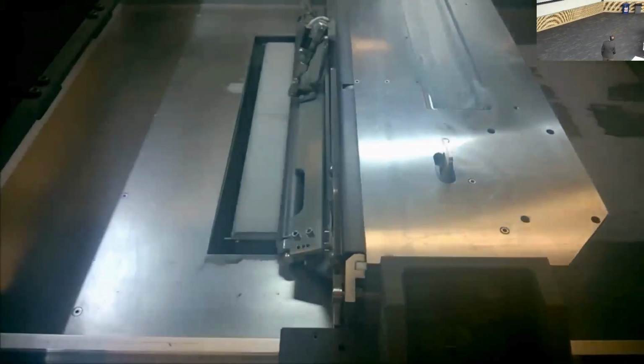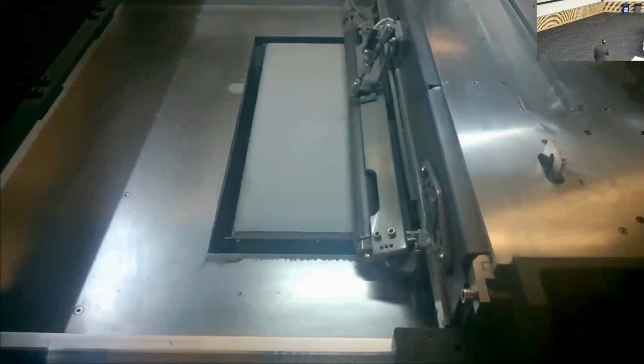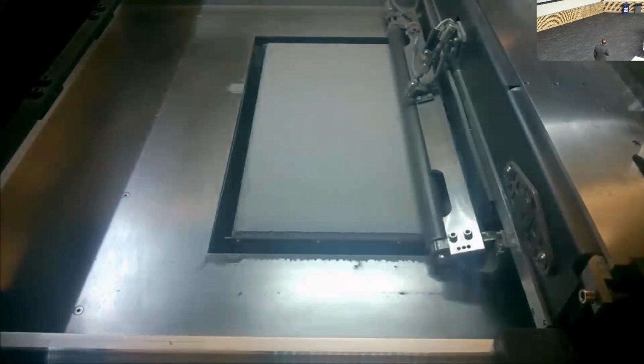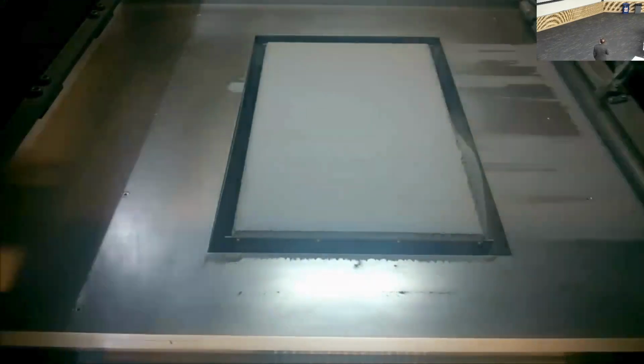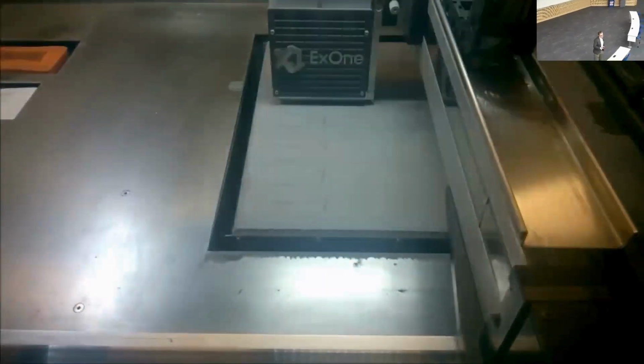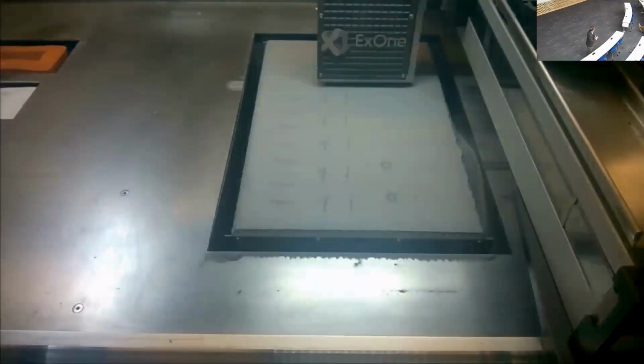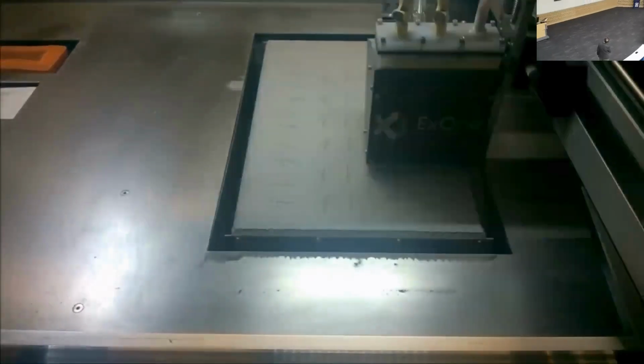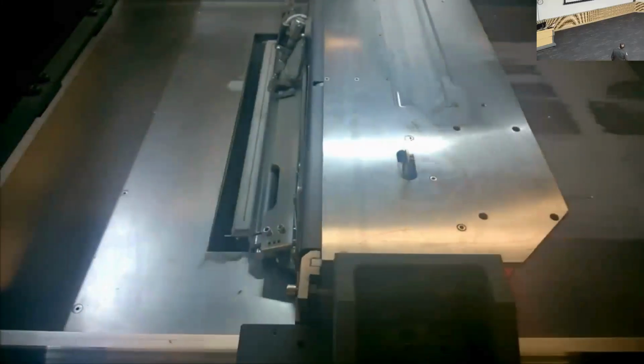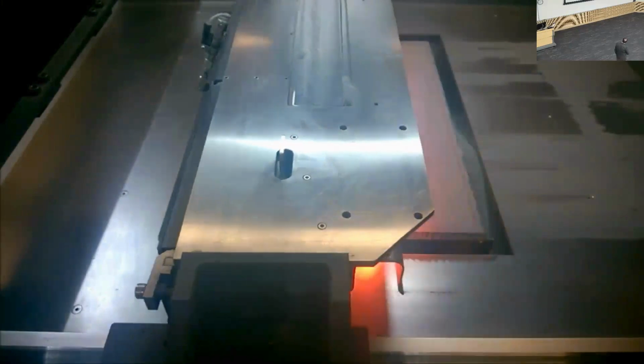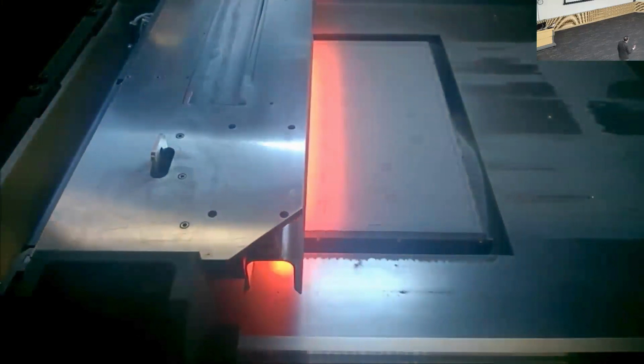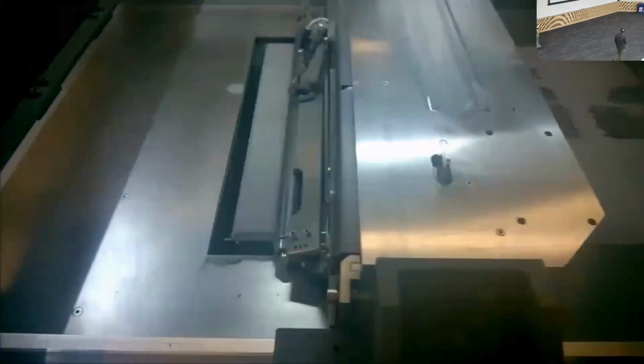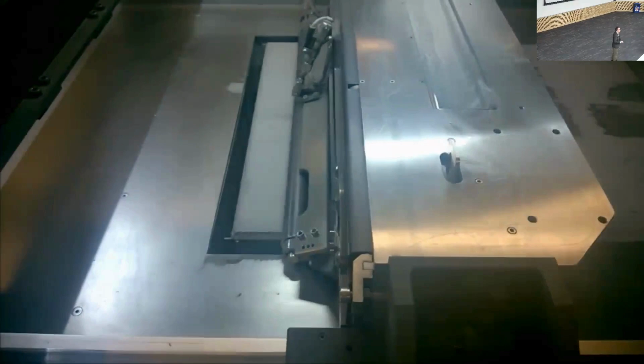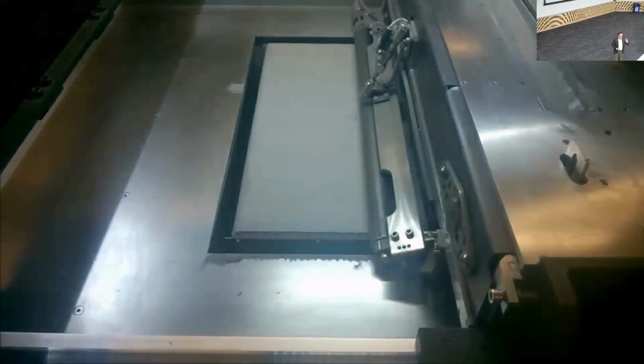So how does binder jetting actually work? What we're doing here is we are laying down a layer of metal powder. We roll it, make it flat. And then in the next step, we are bringing over an inkjet cartridge that you can see here. It's basically like your inkjet printer, but instead of ink, we are printing a glue, right? A binder that is binding particles together in very specific regions that are defined on a 3D model. And then we are drying this binder briefly to evaporate either a solvent or water, depending on what binder you have. And then after this, you consolidate, you cure the binder and are able to take out your part,